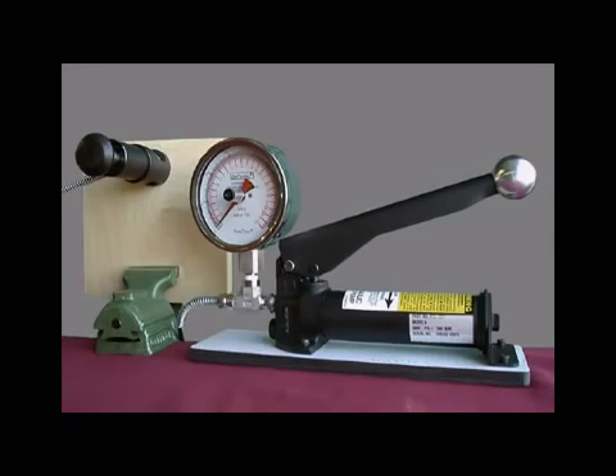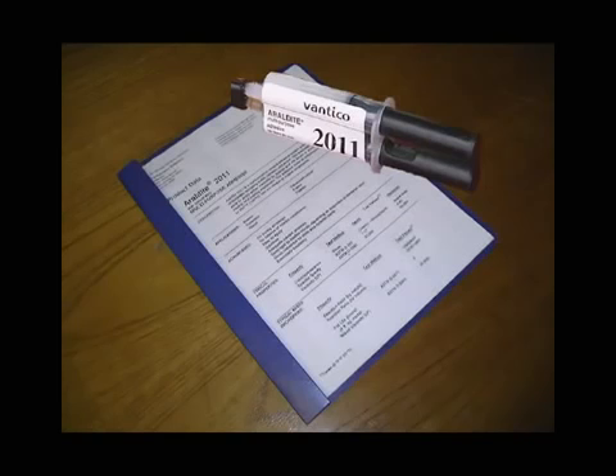Dollies to be placed on uneven, vertical, or overhead surfaces should be held in place with removable tape until fully cured. To prevent adhesive failures, it is important to allow the adhesive to cure per manufacturer's instructions. In some instances, the addition of heat may promote stronger and faster bonding.